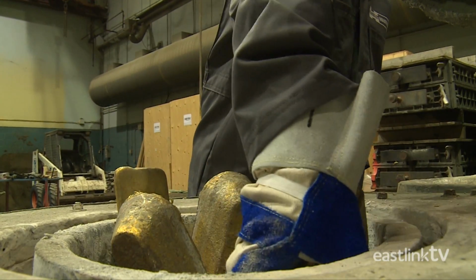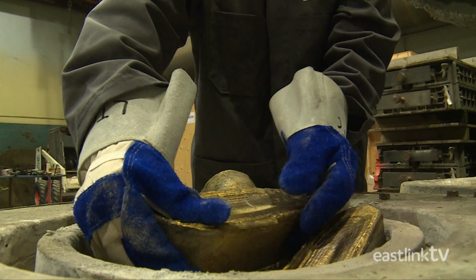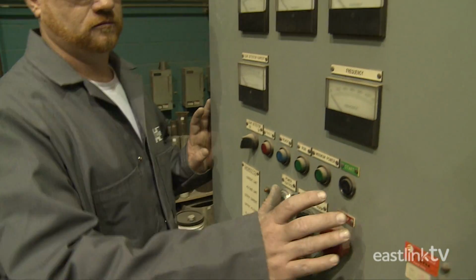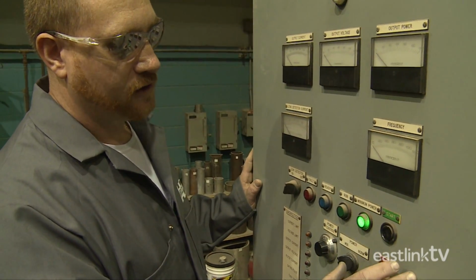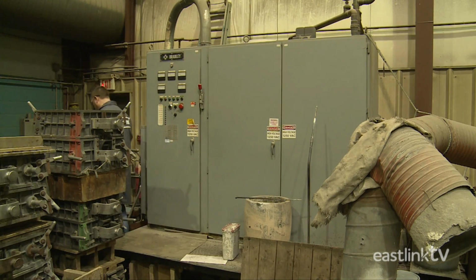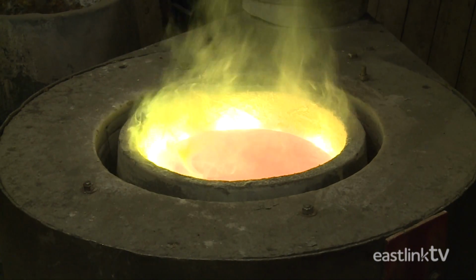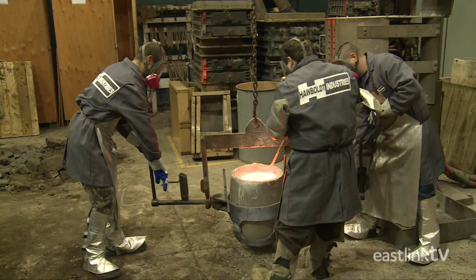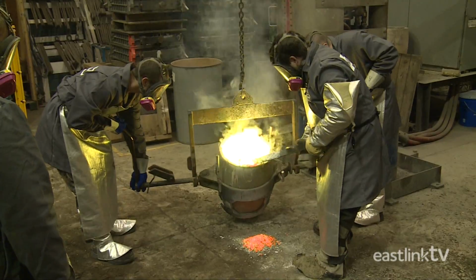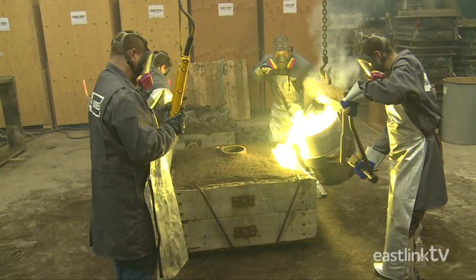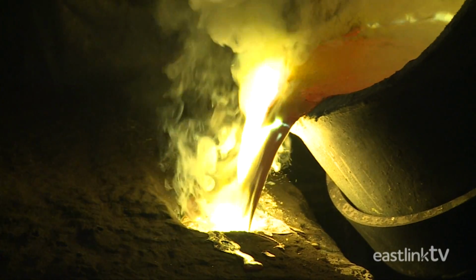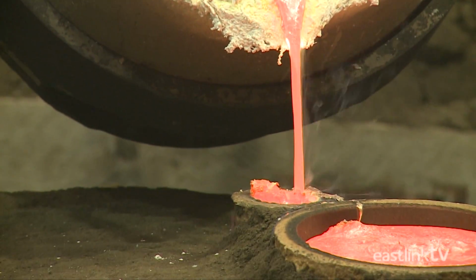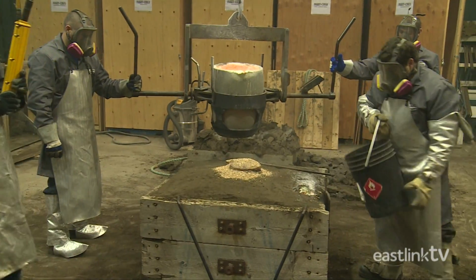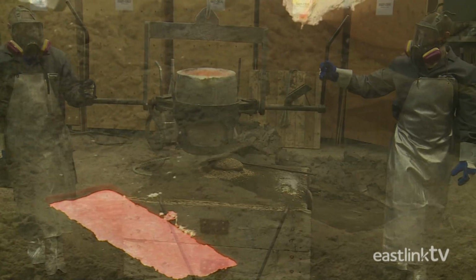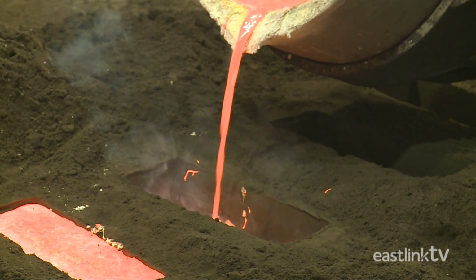The manganese bronze arrives at Hawboldt in large ingots that are placed in one of 3 large furnaces. In this case, an electric arc furnace that's capable of melting up to 600 pounds of material. Once the metal has heated to its melting point, about 1900 degrees Fahrenheit, workers remove it from the furnace and scrape off the top layer, called slag. Finally, the molten material is poured into the sand mold. Once complete, vermiculite is used to cover the riser to ensure minimal shrinkage as the metal cools. Leftover metal is poured into makeshift ingot molds.